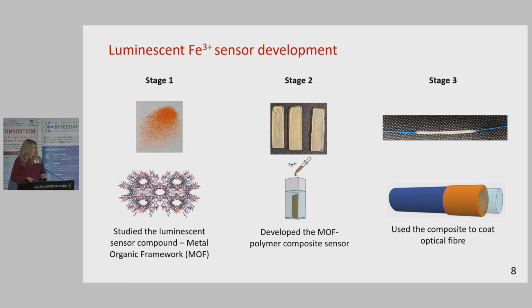In the first part, we needed to find a chemical that would be luminescent and would respond to the presence of iron 3. Then we needed to take this material, a metal organic framework, or MOF for short, and encapsulate it in a polymer matrix to hold the powder crystalline particles together in one place. And then we use this composite material to coat optical fiber and fabricate a practical sensor.